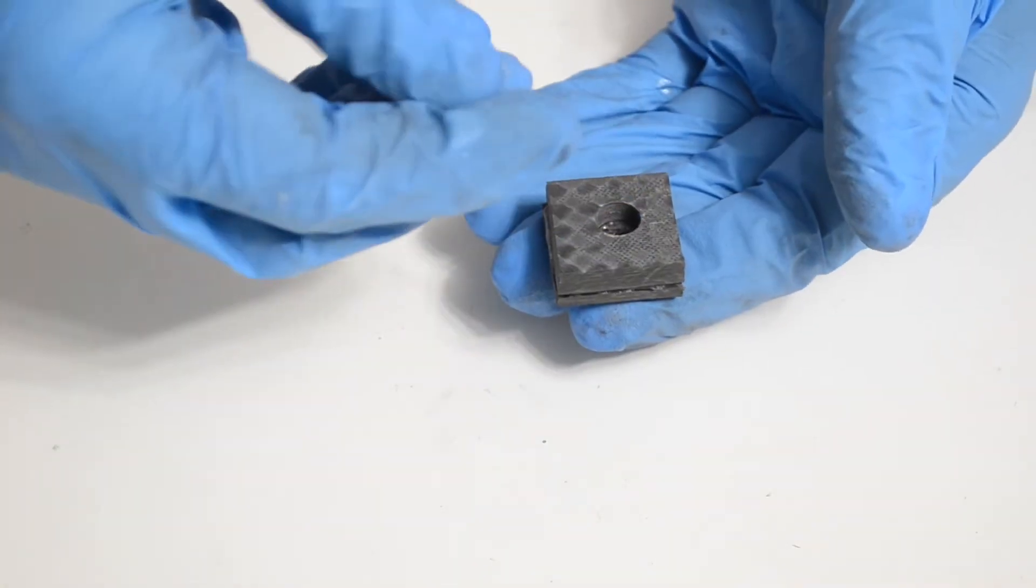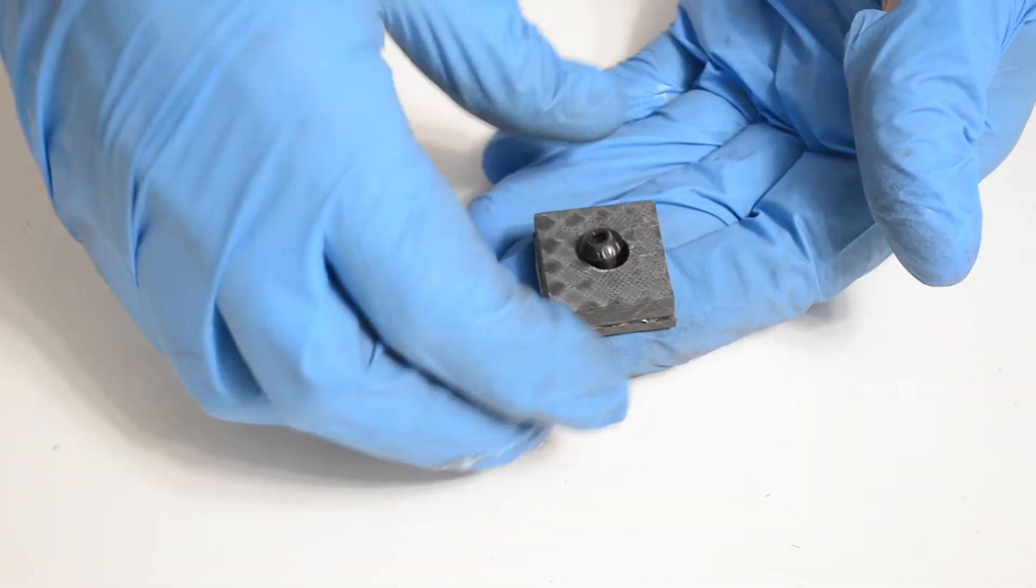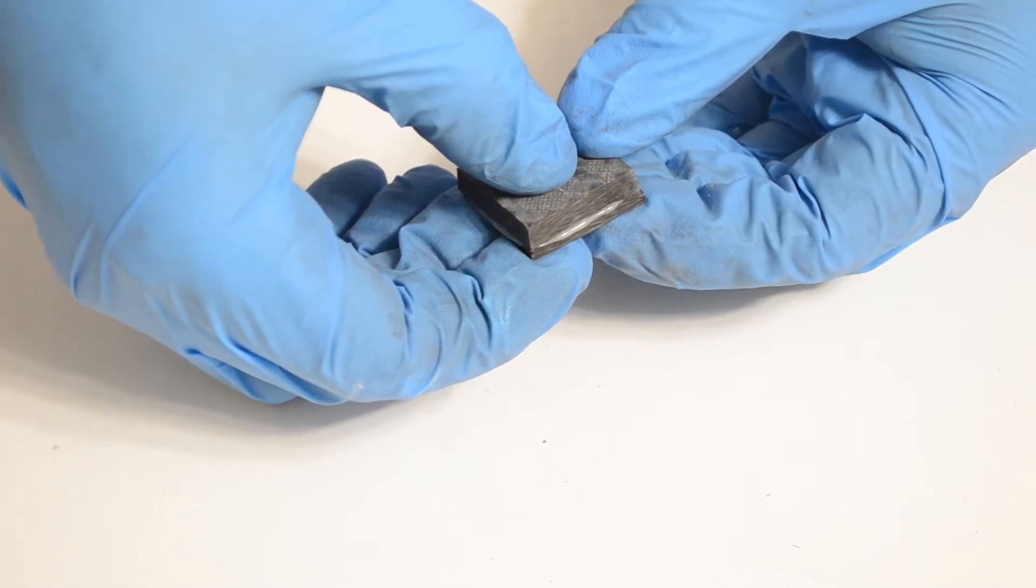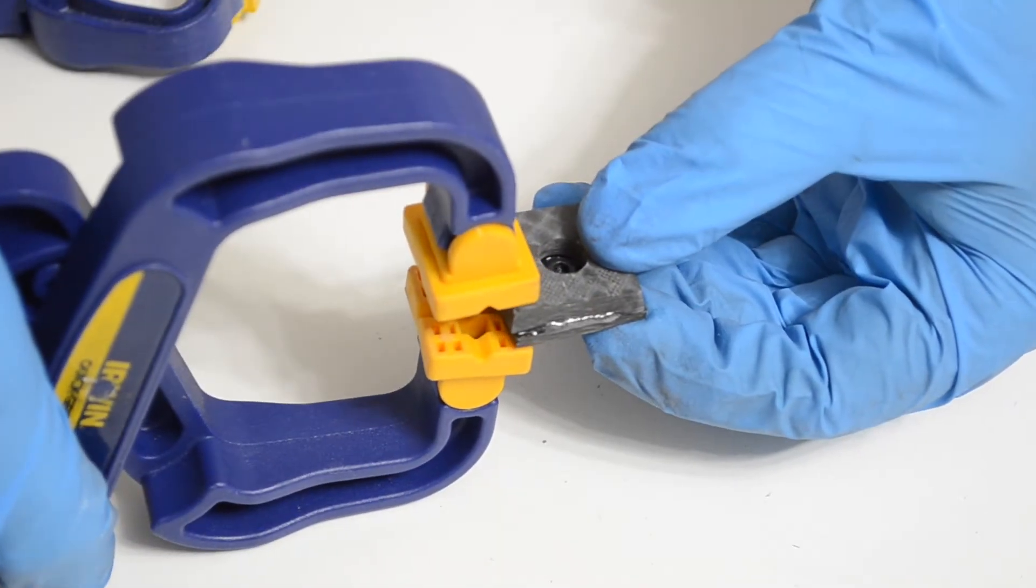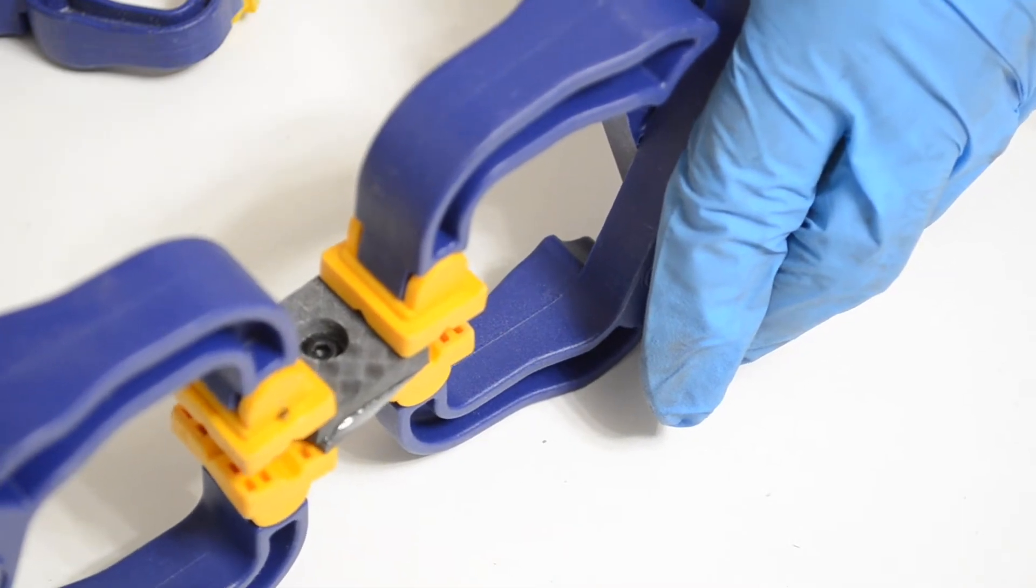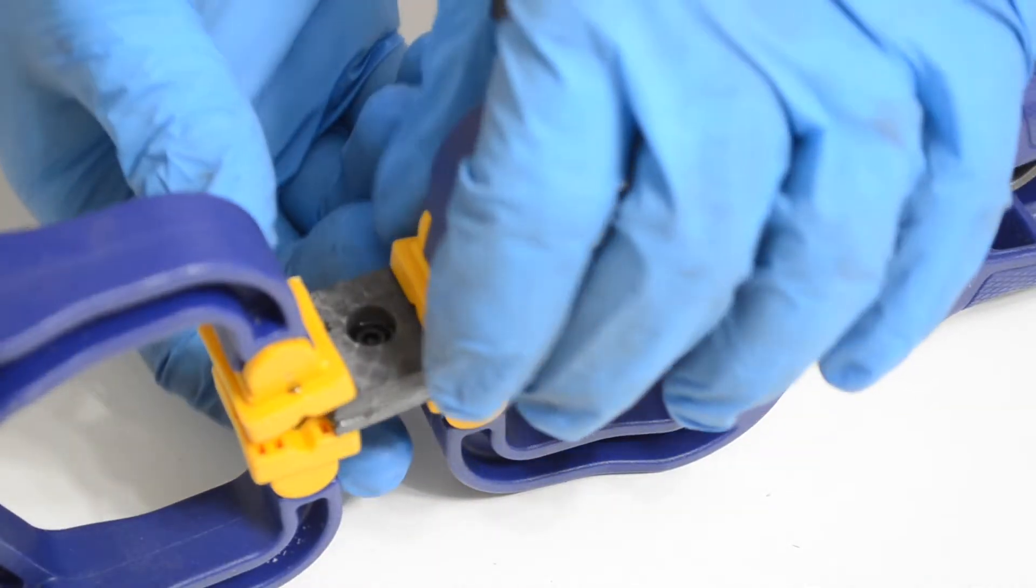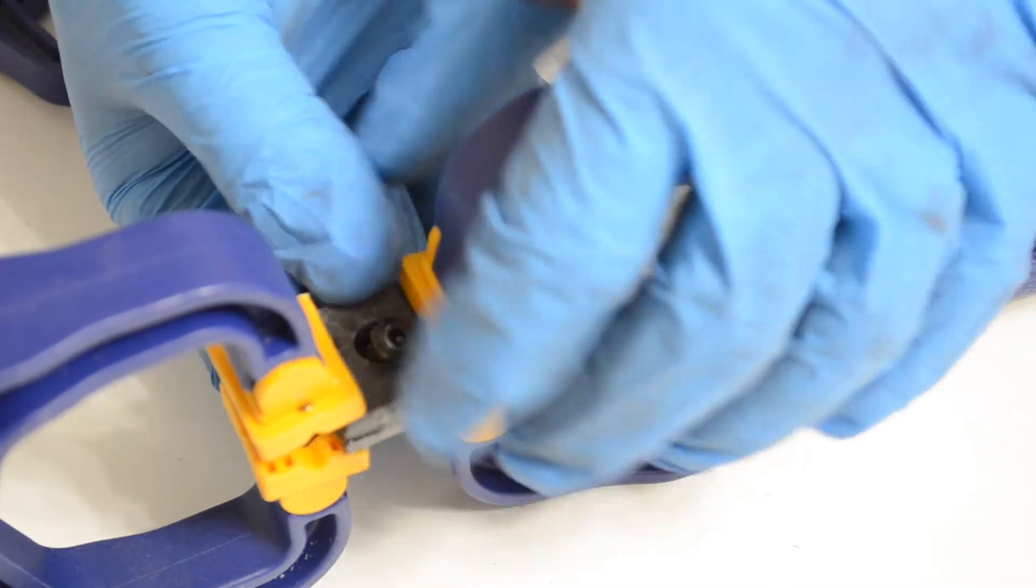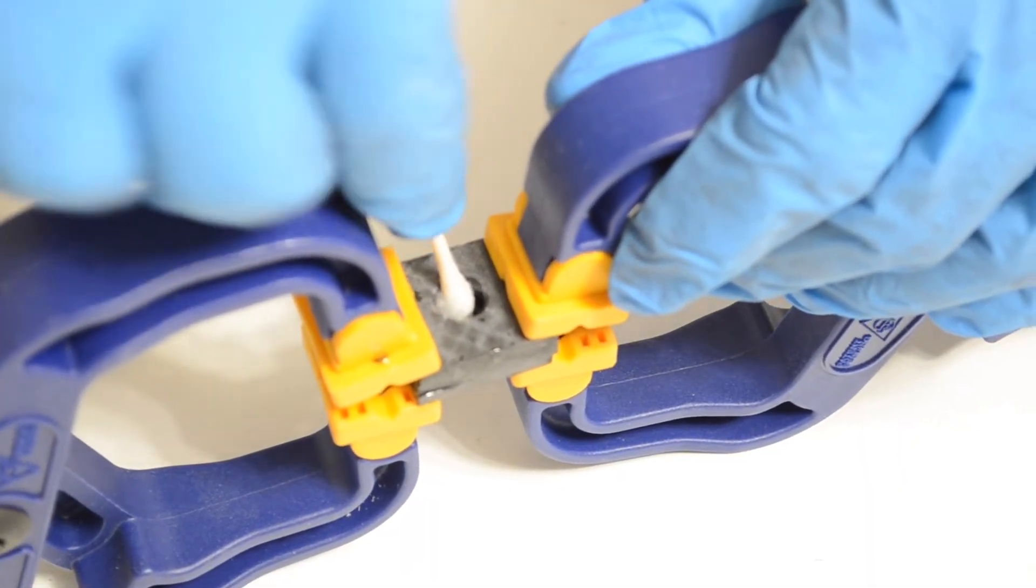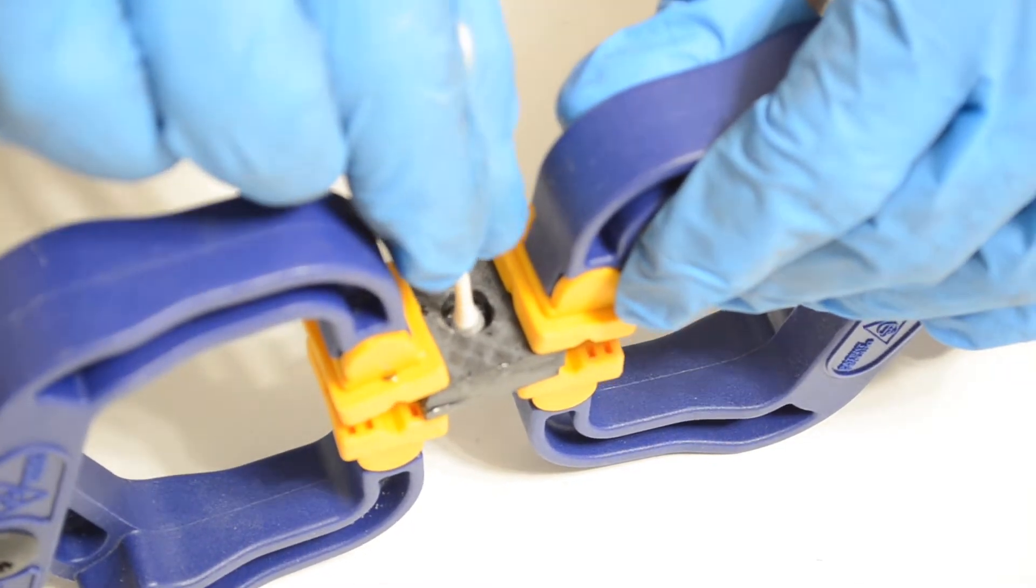Wait for the alcohol to dry completely before bonding. This only took a couple of grams of epoxy and I added a little bit of cabosil to make it more of a paste for bonding these blocks together. To make sure that the holes were lined up after I bonded it, I put the screws in. You can see how the screw head goes through the hole in the 1/4 inch plate, but not the 1/8 inch plate. I left the screws in while clamping it, and then after clamping it I pulled the screw out, cleaned it off thoroughly with some alcohol, and then used a cotton swab, again with some alcohol, to clean any epoxy out of the hole.